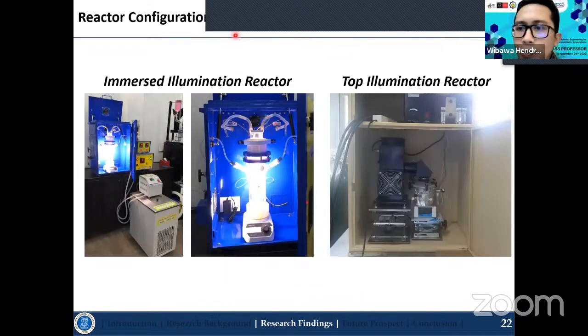Okay, so move on. The two previous works were conducted when I did my master's at University of Twente, and I tried to develop my own laboratory in the chemical engineering laboratory. At the moment, we have 2 configurations of the reactor, which is the immersion illumination reactor as illustrated in this figure, where the lamp is in the center of the photoreactor, in order to make the illumination more homogeneously dispersed in the system, where we also circulate cooling water using a chiller in here to make sure that the reaction process is conducted under ambient conditions, because we use a 300 watt xenon lamp in this system, so it can generate heat during the process.